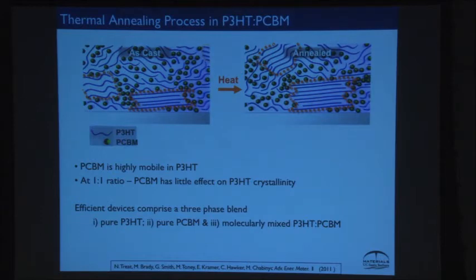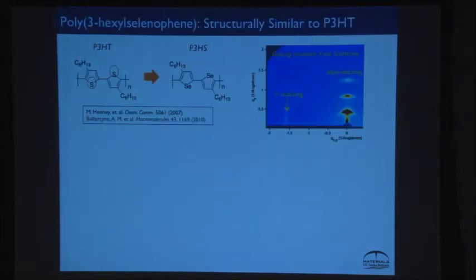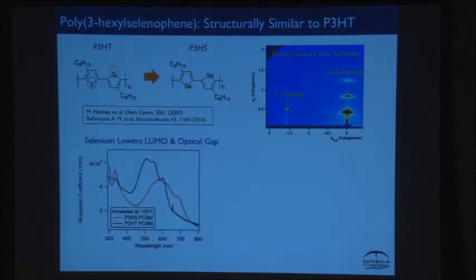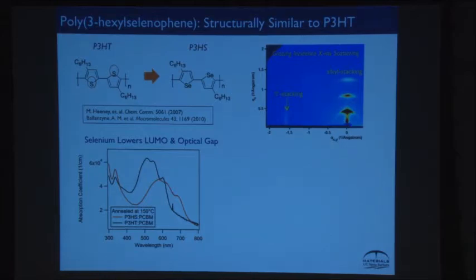And so there are a number of groups that reproduce this. I think everyone agrees. Now you say to yourself, what can I do with that? I want to make cells better. So if I take a material like this, poly-3-hexylselenophene, I do something real simple. I have a collaborator, Martin Heeney, at Imperial College, who can make these selenophene polymers. They have the exact same structure as P3HT. Adding the selenium doesn't change the packing structure very much, but it does change the optical absorption. It goes to a lower band gap, and it has a different overlap with the solar spectrum. And so you might expect these solar cells to be a bit better.